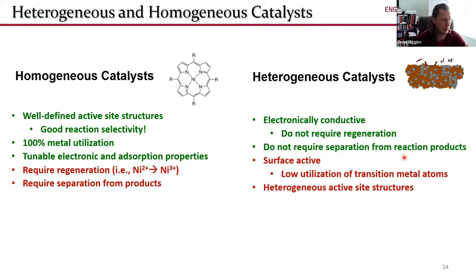But one of the issues is that because catalysis is a surface process, any of these catalyst atoms that are buried in the bulk are no longer available to do the catalysis. They're essentially covered by other atoms. So you have a relatively low utilization of the transition metal atoms in that catalyst. And oftentimes the transition metal atoms are your biggest source of cost.